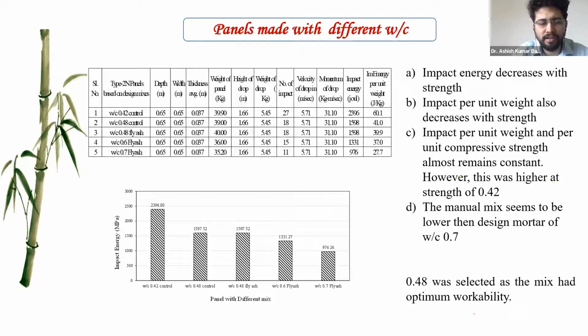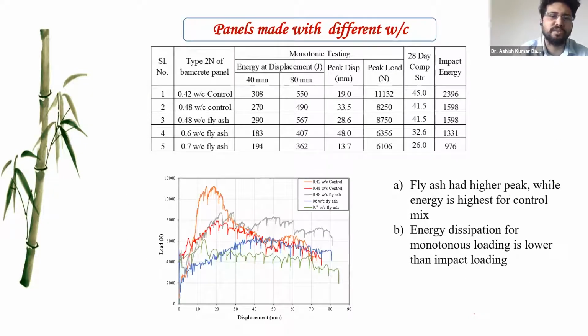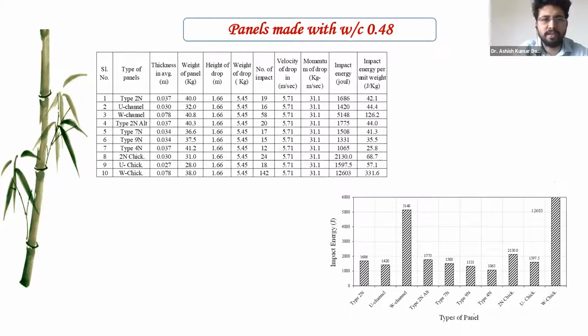As we know, the water to cement ratio of 0.42 showed the maximum impact energy absorption. Similarly, you can see over here, the strength of the panel increased, and the energy absorption capacity in the monotonic loading is high when the design mix mortar was used. Surprisingly, even at 0.7 water to cement ratio, it was found to give more impact energy compared to the normal mason mix mortar. So we can conclude that this normal mason mix mortar is quite inferior even to the 0.7 water to cement ratio.